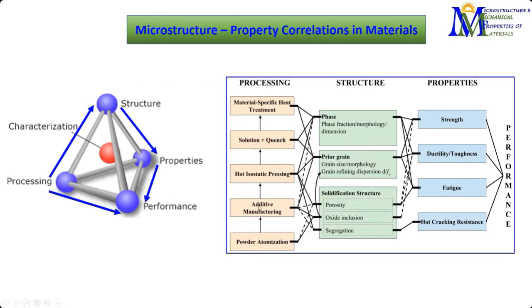So we have seen that in case of additive manufacturing, it has an influence on almost every aspect of the structure, the microstructure, including the phases, the grain sizes, morphologies, the densification, porosity, segregation, etc. And these are leading to variation in important properties such as strength, ductility, toughness, fatigue. Hot cracking resistance is often related to segregation of different phases, and this finally dictates the performance.